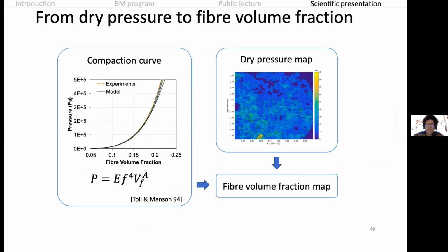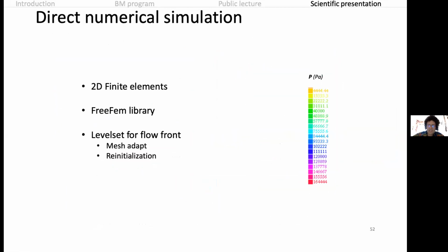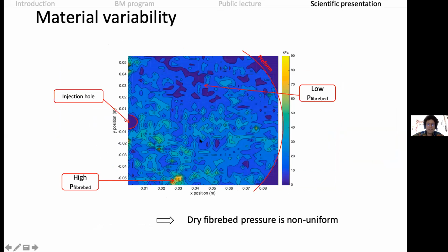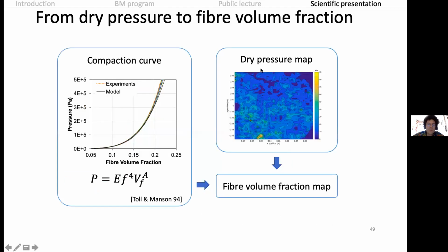Sure. So the idea here, maybe I didn't want to go into too technical a presentation, but I'll still show you. So the idea here is we're not even including the variability because we're measuring the property locally, thanks to the pressure sensor. So it is variable. When you look at this map, it's already variable, but we know the exact value at each location of the pressure measured when we close the mold. And this pressure map can be transferred into a material property map. So typically, I skipped quickly, but the compaction curves and the dry pressure map that we measured give a fiber volume fraction map.